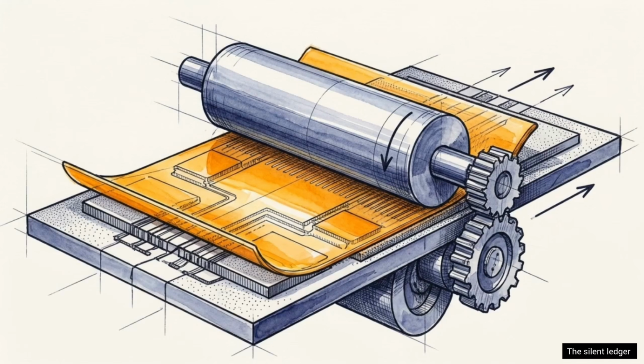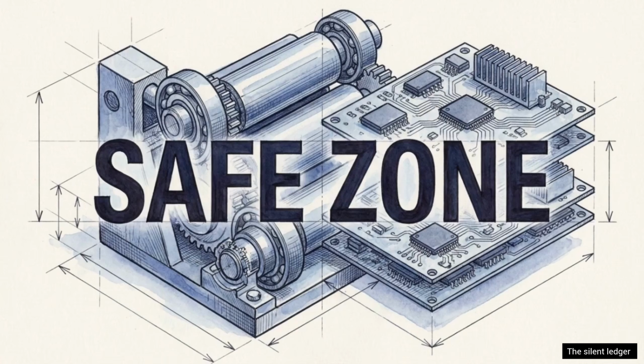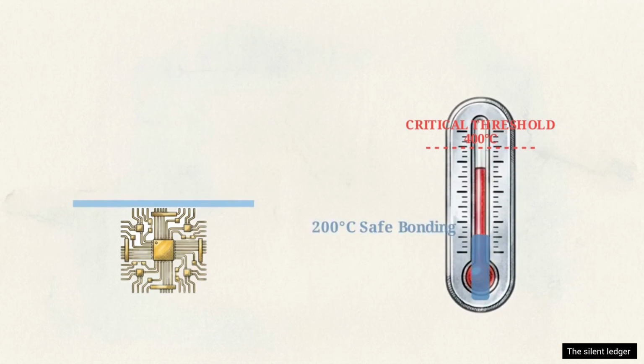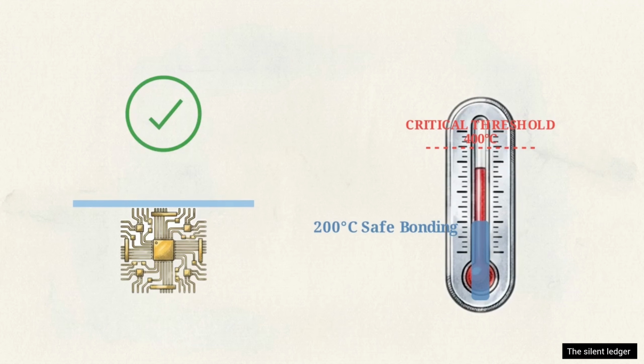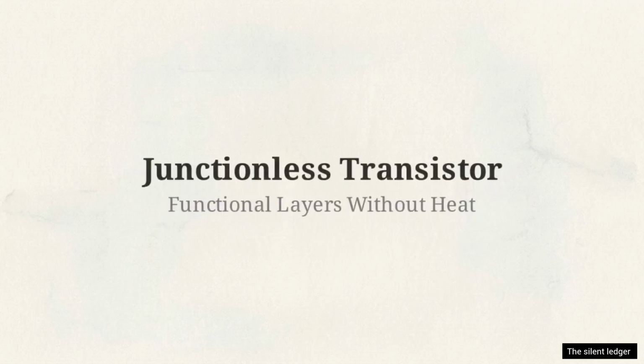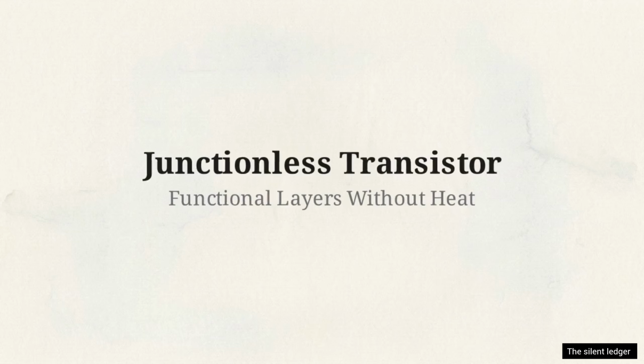Using a roll transfer printing process, the team applies these flexible silicon membranes directly onto a completed circuit layer. The bonding requires a maximum of just 200 degrees Celsius. By treating silicon as a flexible, pre-processed skin, the engineers avoid the 400-degree destruction limit, allowing vertical construction to proceed safely. Making this ultrathin layer functional without heat requires junctionless transistors.